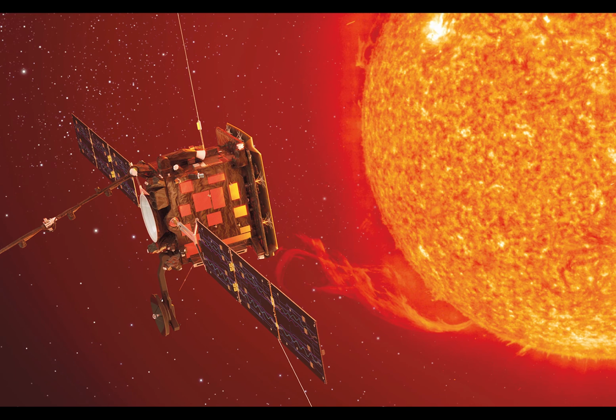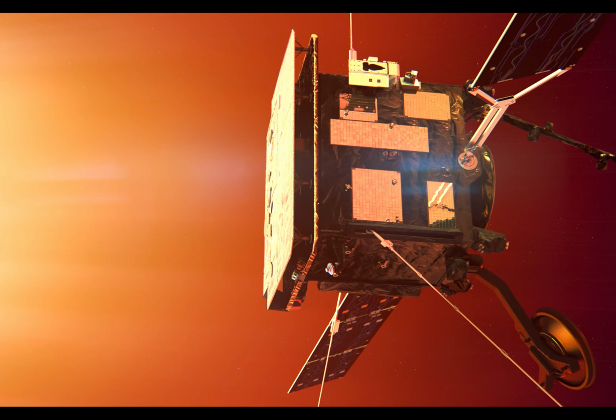Adding extra layers to the shield mitigates the impact but increases the overall payload. Instead, two coatings, solar black and solar white, were shortlisted to coat the titanium. Developed by mechanical engineering company ENBIO, in collaboration with ESA and Airbus Defence and Space, both coatings are made of calcium phosphate and applied to titanium using a technique called co-blast. This involves grit blasting away the titanium surface oxide layer to chemically bond the coating, fixing it to the substrate metal. The black calcium phosphate that makes up solar black gives it high emissivity and high solar absorbance properties, helping it mitigate extreme solar radiations.